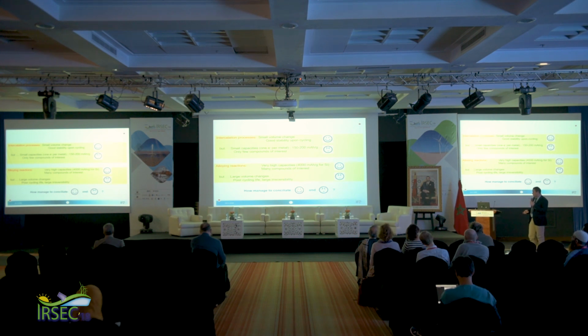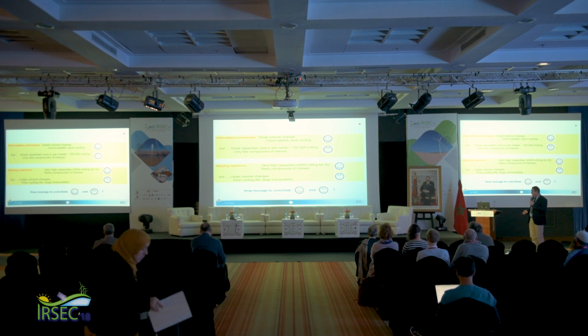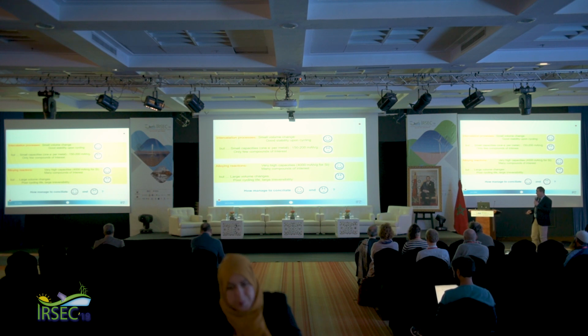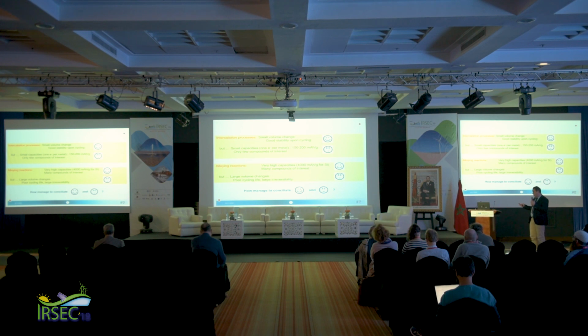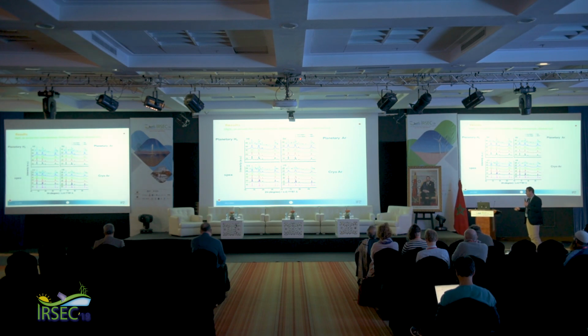The other process is the alloying reaction, for example in silicon, where we have really high capacity. But there are a lot of issues with silicon that hinder its application, in particular the large volume expansion, which is a big problem and leads to pulverization of the electrode. So the question is how to reconcile these two: how to have low volume change and high capacity. It seems hydrides can fit in this direction, with high capacity and rather low volume change.